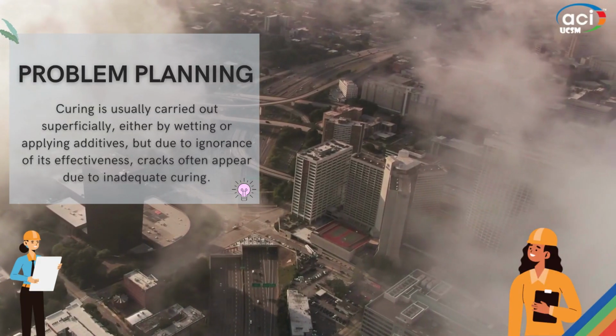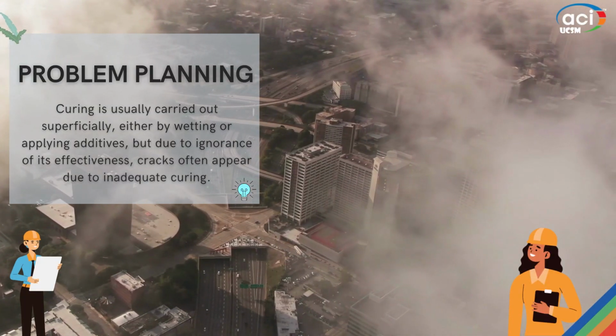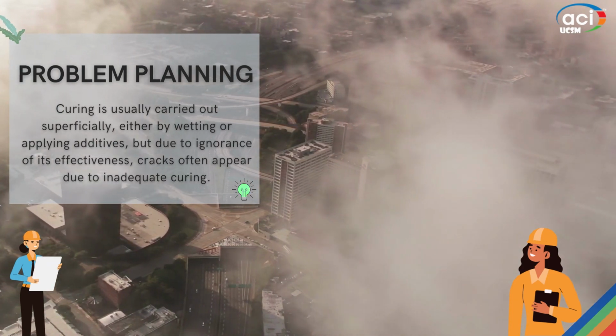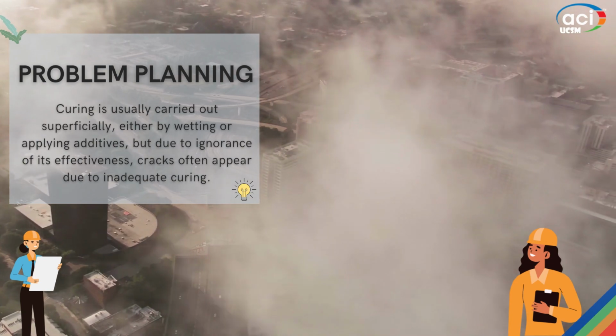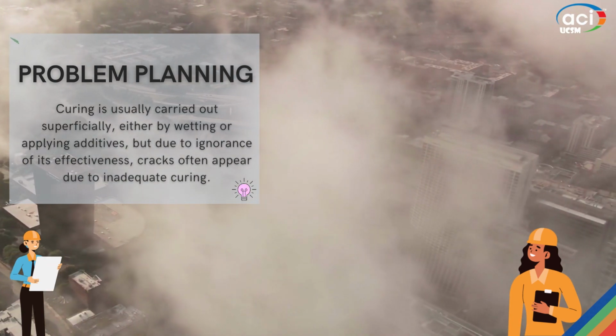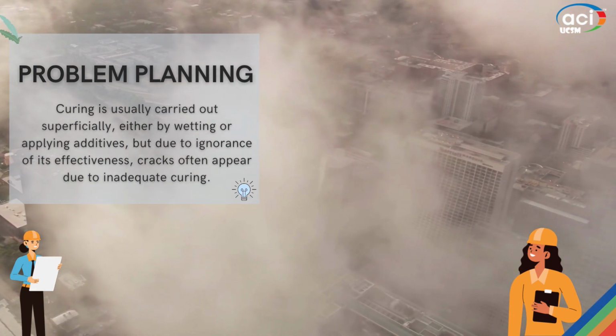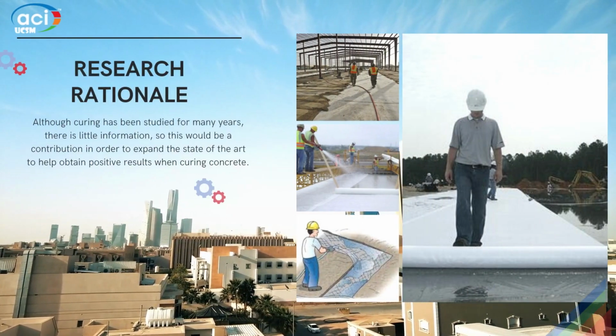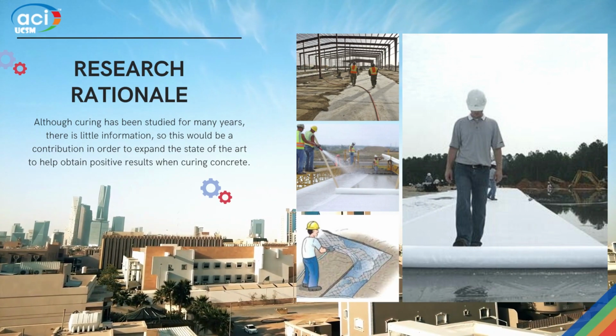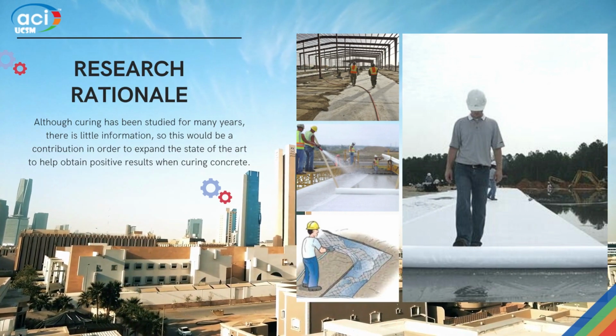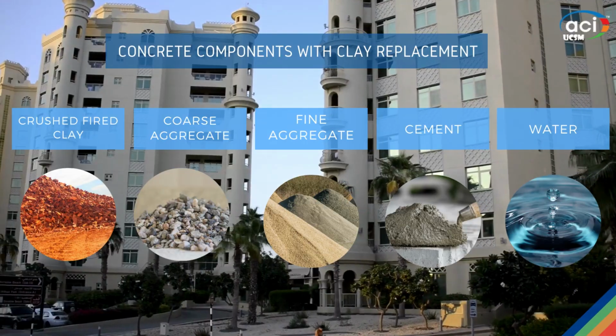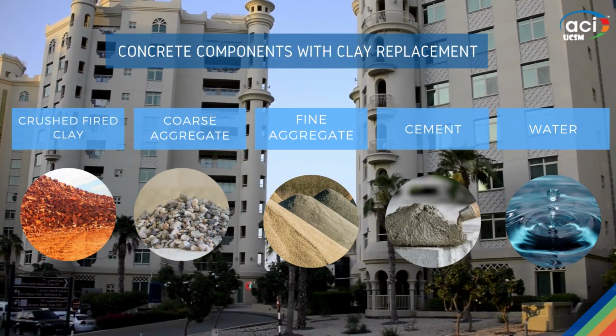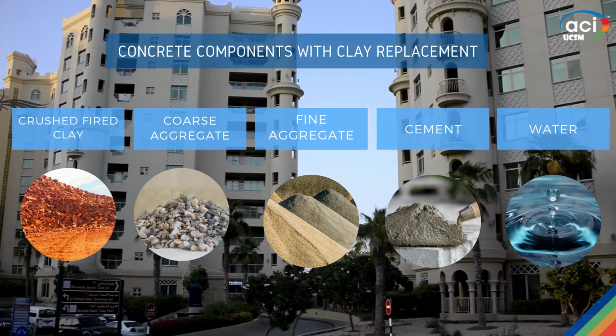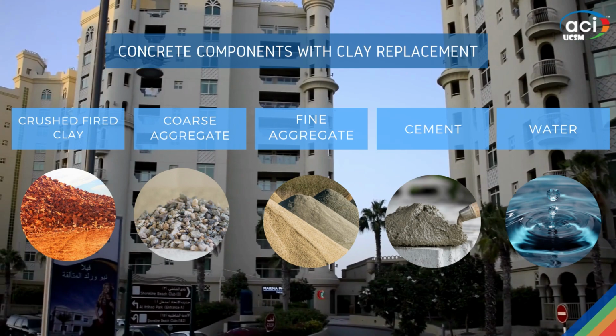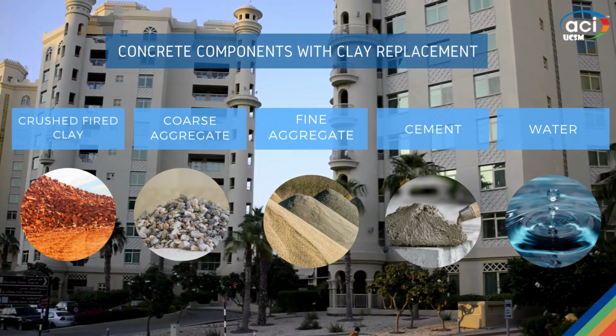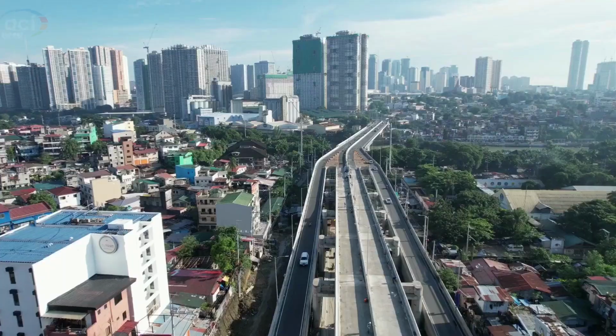The problem arises on site because, at the time of carrying out the different concrete-based construction, it is generally superficially cured, or with the use of an admixture, and this curing is not the same as curing by immersion, which is carried out in the laboratory to verify a correct mix design. This curing difference between the concrete used on site and the one evaluated under controlled conditions in the laboratory will give different mechanical properties. With saturated crushed baked clay in partial replacement of the coarse aggregate, we can perform a curing from inside the concrete element, and in this way we are able to provide water not only superficially but also from the inside.